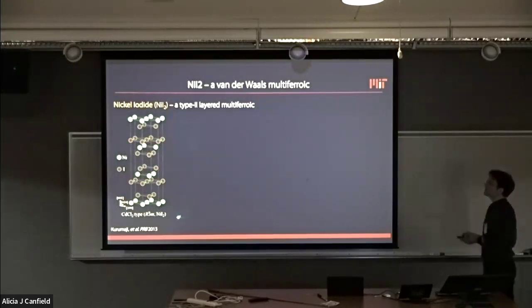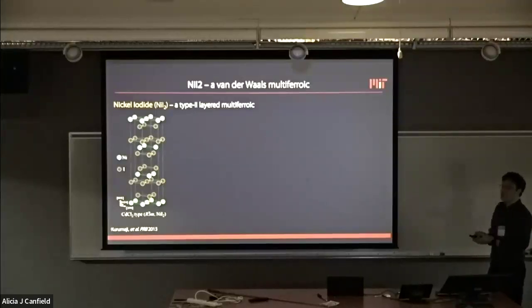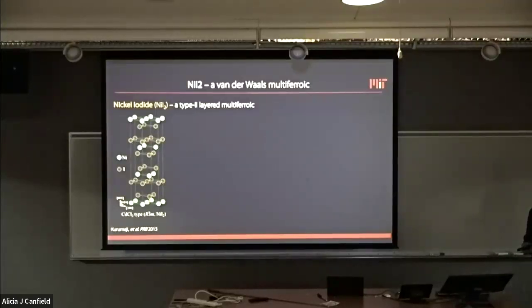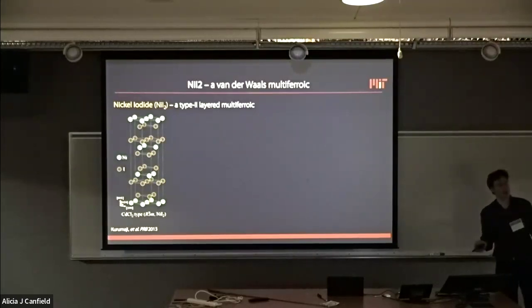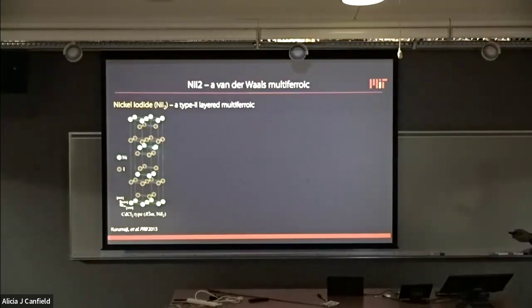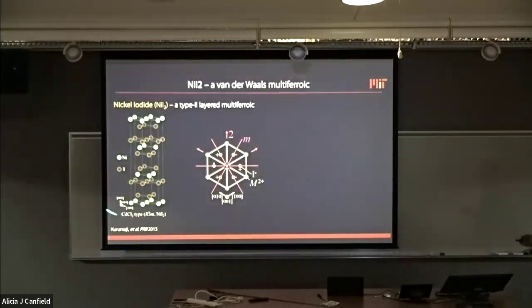So this is the structure of nickel iodide. It's a van der Waals material, so it's broken into layers. These layers are weakly bonded to each other, and you have the nickels that form 2D triangular lattices, the triangular planes, and they're coordinated to the iodines out of it. So if you look at just a single plane, it's a very similar structure to the transition metal trihalides, but the nickels form a triangular lattice. And this is the rhombohedral structure. This is the structure that the material takes up at room temperature.